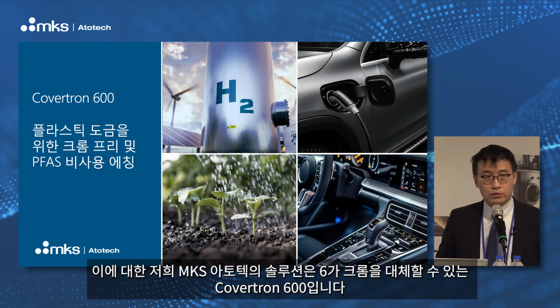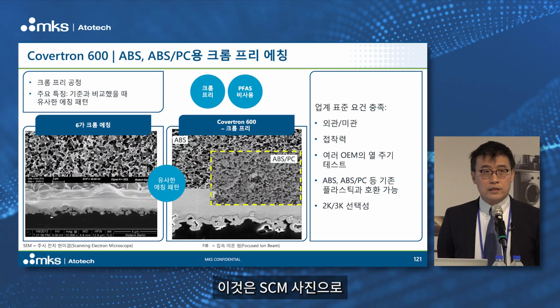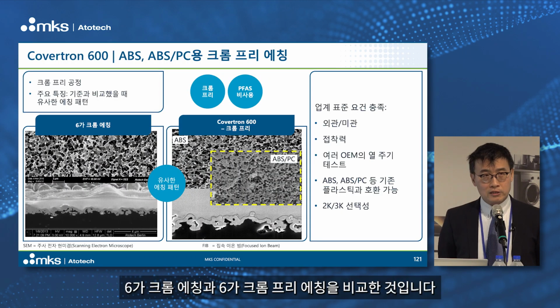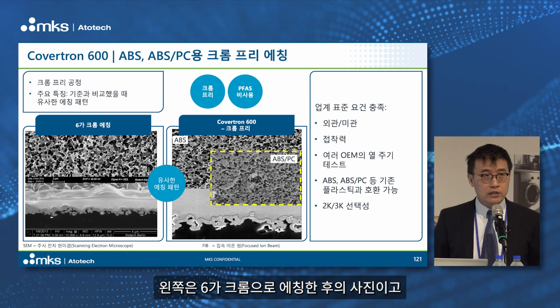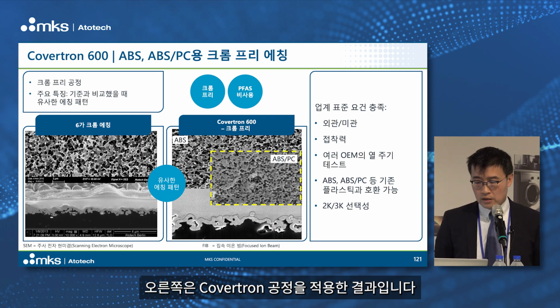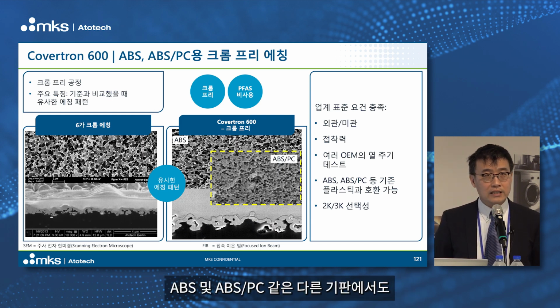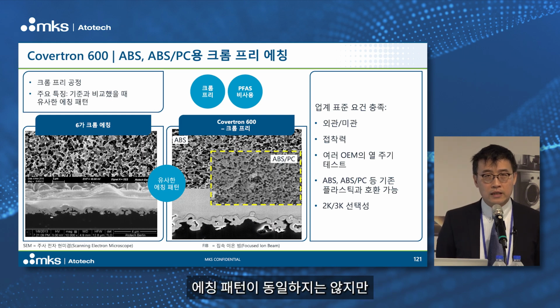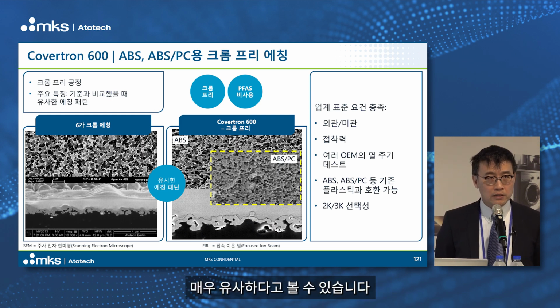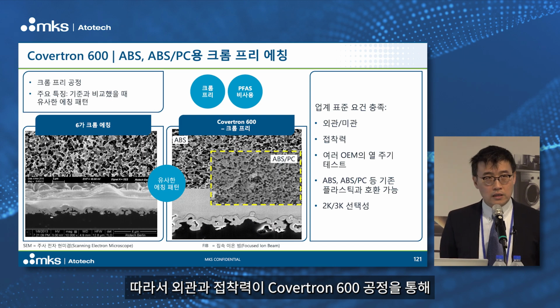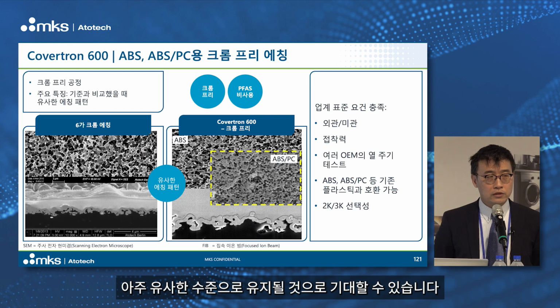Our solution is Covertron 600 as a replacement of chromium 6. You can see here the SEM pictures comparing Chrome 6 etch and the Chrome 6 free etch from our process called Covertron. On the left-hand side is a Chromium 6 SEM picture after etching. On the right-hand side is the Covertron with different substrates like ABS and ABS-PC. The etching pattern is not identical, but I would say very similar. So we can expect that the appearance and also adhesion is very similar with the Covertron 600 process.